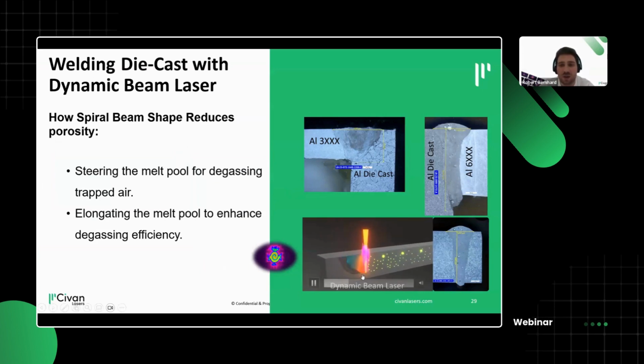And I think this is a good illustration where our high frequency beam steering elongates the melt pool, makes sure that the capillary stays open, and also collects the porosity and the bubbles from the side that occur during welding, but also the ones that are already diluted into the material.